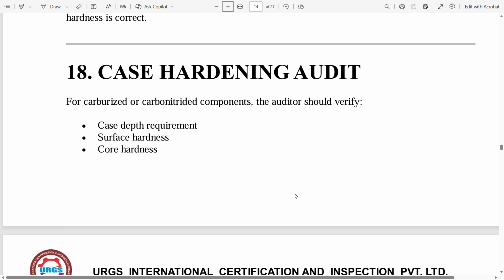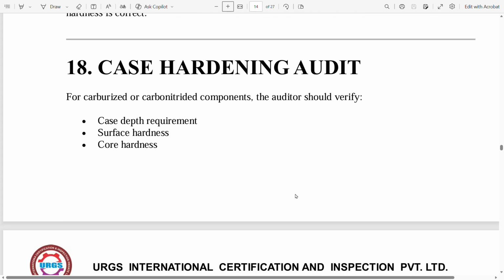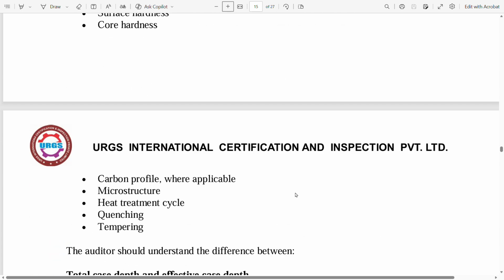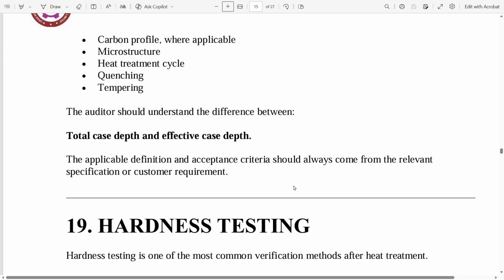Then 18th, case hardening audit. For carburized or carbonitrided components, the auditor should verify case depth measurement requirement, surface hardness, core hardness, carbon profile where applicable, microstructure, heat treatment cycle, quenching, tempering. The auditor should understand the difference between total case depth and effective case depth. The applicable definition and acceptance criteria should always come from the relevant specification or customer requirement.